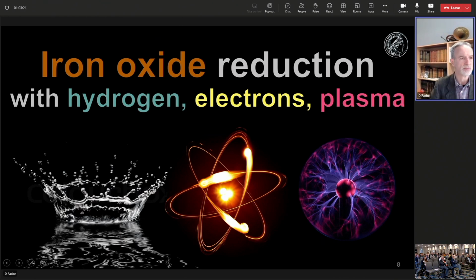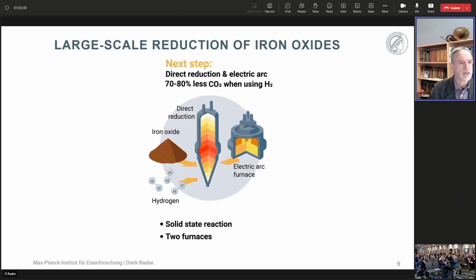So I will talk in this presentation about three variants, namely reduction of iron oxide by hydrogen, by electrons, and plasma. And I start with the well-known textbook example of direct reduction, which you have around the globe already in different flavors, essentially a static shaft bed reactor, where the word static is not quite correct because under the swelling and shrinkage and change and abrasion, you have quite a lot of mechanics and dynamics in these ovens. But in principle, they currently operate under methane or different syngas mixtures, which in part already contain hydrogen. And then you create a material that is porous iron, referred to as iron sponge, that is then downstream fed, for instance, into an electric arc furnace, as is sketched here.